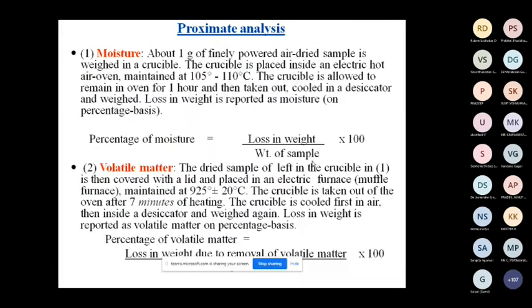Start with proximate analysis. I don't know how many are familiar with it. Proximate analysis means determination of moisture content, volatile matter, fixed carbon, and ash. I will explain in simple terms how we do it. You take about 1 gram of sample, weighed in a crucible. The crucible is placed inside an electric hot air oven maintained at 105 to 110 degrees C for 1 hour. Then you take it out and find the weight loss. That loss you account for as moisture. The percentage moisture equals loss in weight divided by weight of the sample. So this will give the moisture.